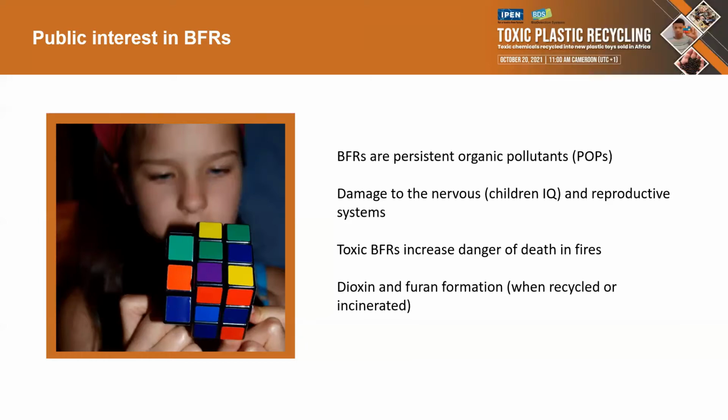All items containing brominated flame retardants emit brominated dioxins and furans when those items are heated up, incinerated, or burned. The same happens when products or waste are recycled and heated in the recycling process. Then the final products can also contain brominated dioxins and furans.